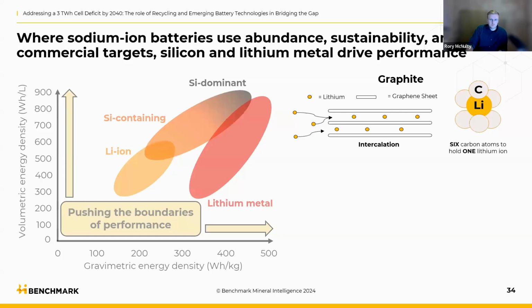So to understand the silicon anode and the material it's looking to complement, we need to understand a graphite anode first. Graphite operates by lithium intercalation. Lithium ions move through the liquid electrolyte. They're inserted between graphene sheets, and 1 lithium ion is stored per 6 carbon atoms in this framework.